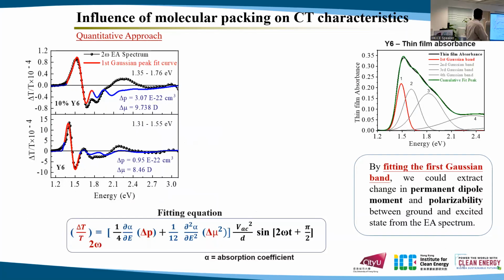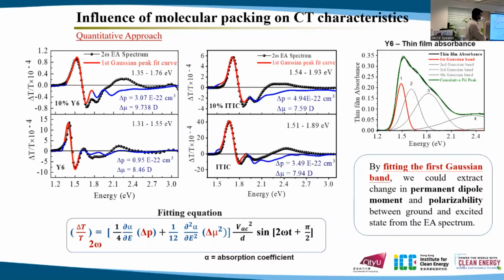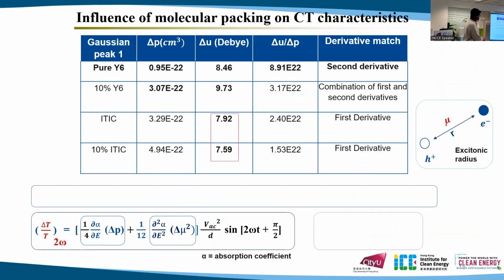For that, we have the EA equation, and we know the applied voltage and thickness. Then we can do fitting using the first Gaussian band of the thin film absorbance. We use that data to do the fitting and extract the delta P and delta U values. This table shows the extracted delta U and delta P values.